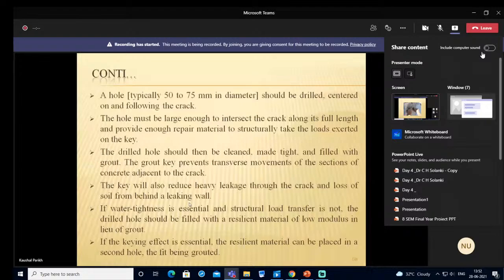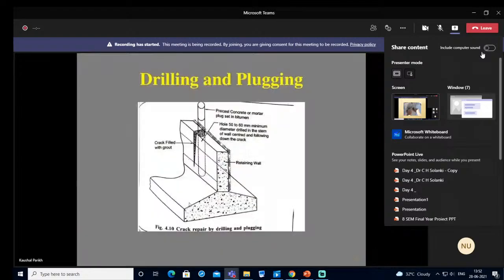Here, the key will also reduce the heavy leakage through the crack and loss of soil from behind the leaking wall. Water tightness is one of the important criteria over here, and the structural load transfer is not. The drilled hole should be filled with a resilient material with a low modulus of elasticity. Here, the key effect is essential, and the resilient material can be placed in a second hole to fit being grouted, as shown in the figure.